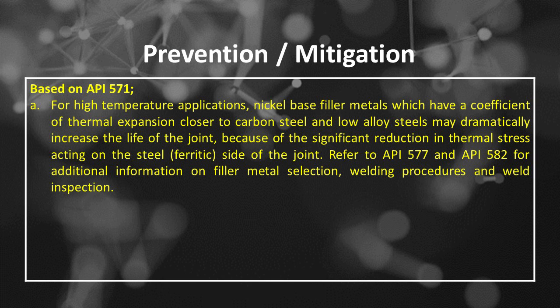The first is for high-temperature applications. Nickel-based filler metals, which have a coefficient of thermal expansion closer to carbon steel and low-alloy steels, may dramatically increase the life of the joint, because of the significant reduction in thermal stress acting on the steel, ferritic, side of the joint. Refer to API 577 and API 582 for additional information on filler metal selection, welding procedures and weld inspection.